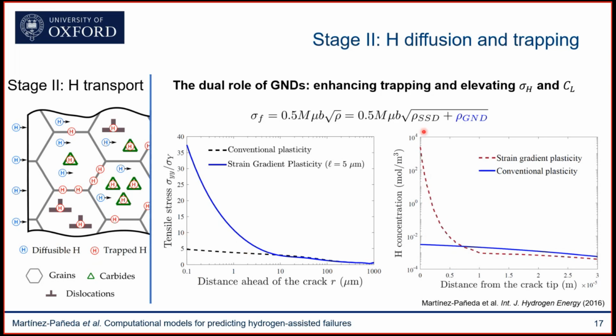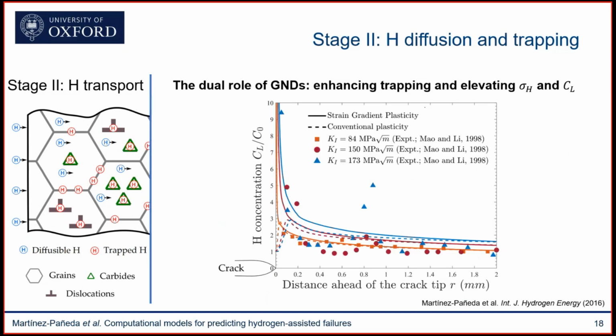You can see it here. This is a log-log plot where you're predicting much higher hydrogen concentrations when you account for the role that GNDs play on crack tip stresses. And this is quite important because, first of all, we see that only by accounting for the GND effect are we able to reproduce what we see in the experiment. So these are measures of hydrogen concentration ahead of a crack. And you can see that only by accounting for the GND effect, the solid lines, are we able to capture two trends that we see in the experiment: that the hydrogen content increases with applied load, and that the hydrogen content significantly increases near the crack tip.